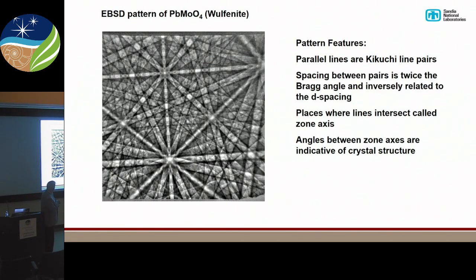The other thing you notice is all these intersection points between the various bands. Those are the zone axes. And of course, the angle between the zone axes tells us an awful lot about the crystal structure that we're looking at. So if we can measure the angles between these planes and the angles between the zone axes, we can tell you what the crystal structure is. And we can tell you what it matches to. And in fact, we can tell you the orientation of the grain that it came from very accurately. Typical accuracies are sub-degree with this technique, so maybe half a degree or less in orientation accuracy.